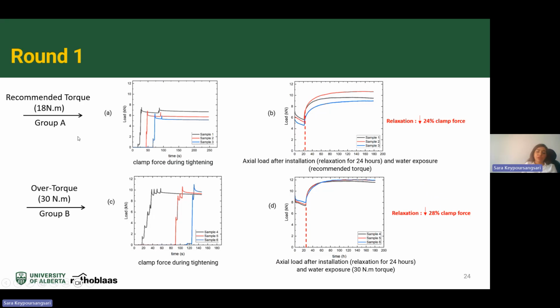In group A, where we increased the torque up to 18 Newton meter, you can see how the load increased during the tightening, and only a few seconds after installation, this load starts decreasing. This phase is called relaxation, and it happens for all connections and all fasteners. But it depends on the material, and there wasn't much data about how this relaxation phase would be in timber connections. So we waited about 24 hours to see how this relaxation phase would be.